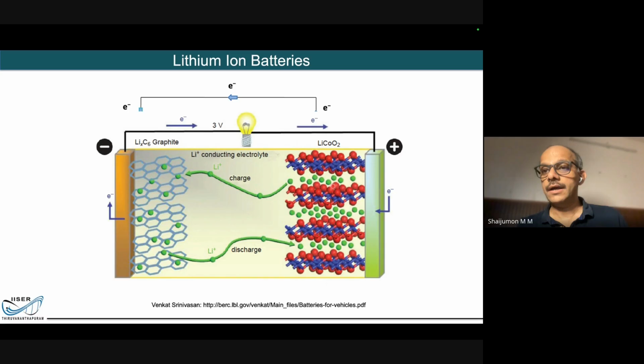So I have to charge the battery initially. When I say charging the battery, it is sort of an oxidation happening here, because lithium cobalt oxide is releasing electrons and the lithium. These electrons cannot go through this medium because it can only permit lithium ions. So the electrons will take the external path. When you're charging it, that's what you get to see. The electrons take this external path and get to the anode. In the meantime, the lithium ion travels through this liquid electrolyte, because thankfully you have a porous separator.